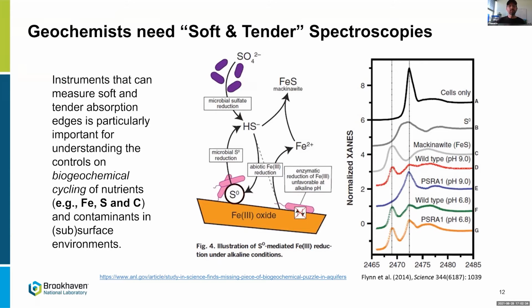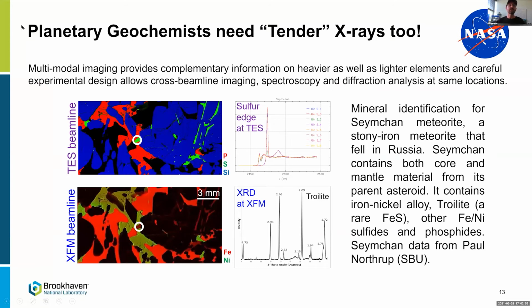So we have some microscopes that are coming online that I mentioned that would give us carbon spectroscopy at the nanoscale. We already have some bulk spectroscopy for the carbon edge at the SST beamline. I don't have an example to show you, but I can put you in contact with folks that can make the measurements at the carbon edge. You already heard from Paul and TES. XFM can also do the sulfur K edge, but cannot go any lower down to the phosphorus edge. I won't say much more about TES because you heard all about it from Paul, but just to say we do a lot of multimodal work between the microprobe in the hard and tender energy range.